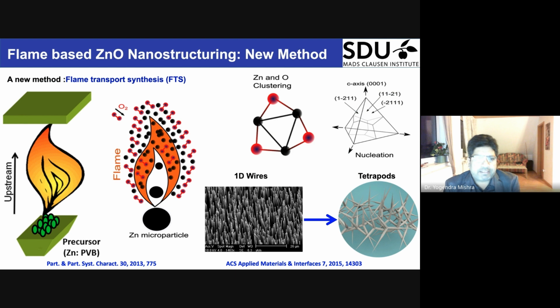Well, you might be asking the question, how one could build these tetrapods? What is the process? So, basically, this process is very simple. In the recipe I developed, we take the precursor material in a polyvinyl butyral mixture, fill it into the crucible, and put it into the oven at high temperature, around 900 degrees centigrade. During the process, due to the temperature, the polymer burns. It takes the zinc microparticles up and converts them into atomic vapor, and then with the help of native oxygen, you have a growth from the solid vapor solid growth form of nanostructures.